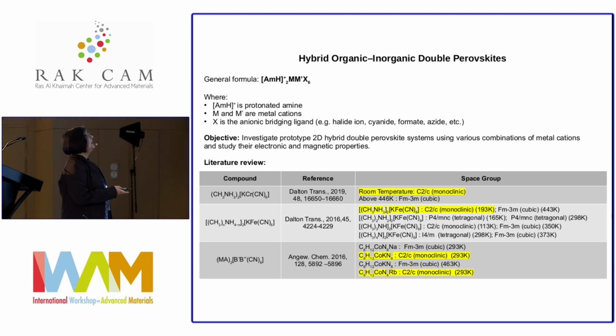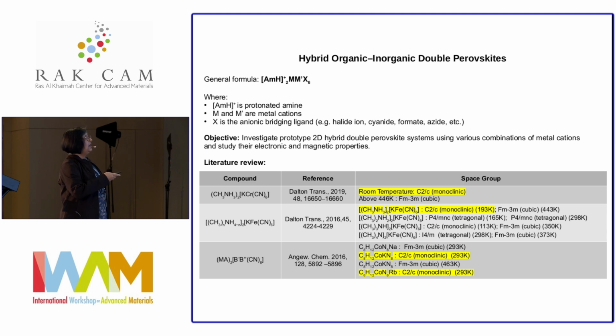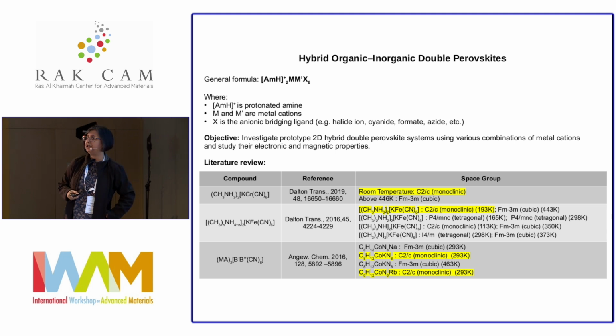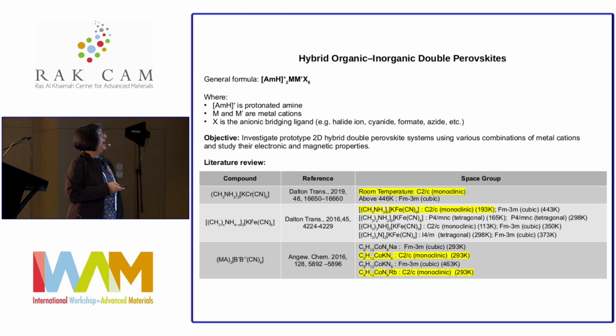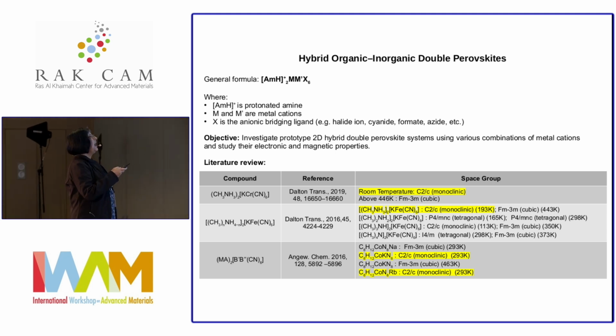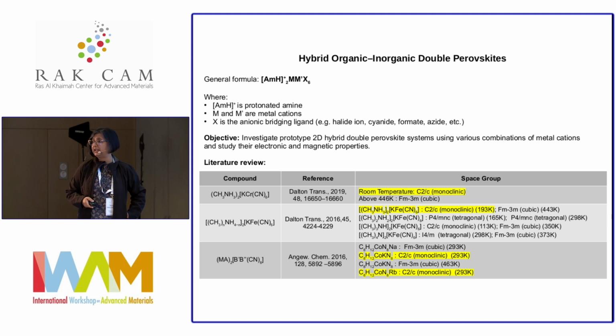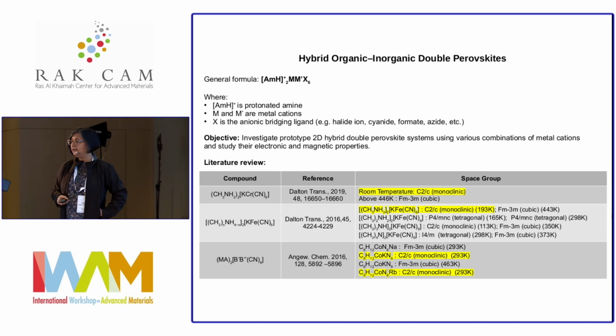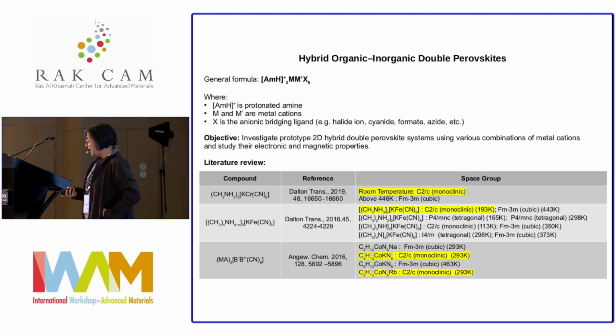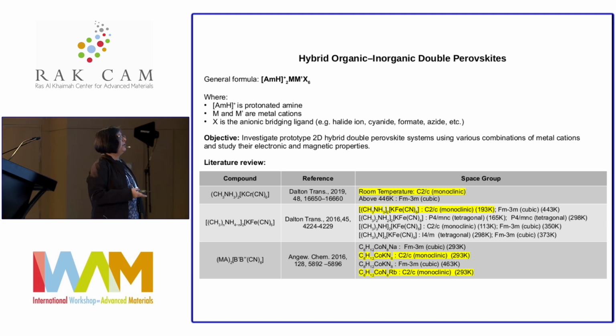So I give you some of the references which are given here, where they have indeed put some organic protonated amine at the A site. And then they have used basically the cyanide as the linker. And since you have this 1 plus and the CN 1 minus, then you need to put a monovalent and a trivalent. And so they have put basically potassium in most of the cases and chromium or iron. Now, we want both of them to be transition metal, not with the potassium.